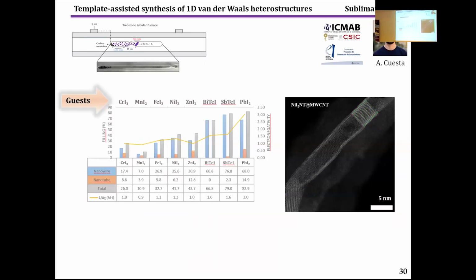Okay, we also employed this approach, the sublimation, to encapsulate a variety of systems. This work has been developed by Alejandro Cuesta. Here he used multi-wall carbon nanotubes to encapsulate different crystals with different properties, for example, with magnetic properties or of interest in thermoelectrics. And he also made a correlation between the electronegativity of the metal and the formation of nanotubes. Apparently, there is no correlation with the formation of nanotubes, but there is an important trend, an increase in filling when the difference of electronegativity of the material is high.